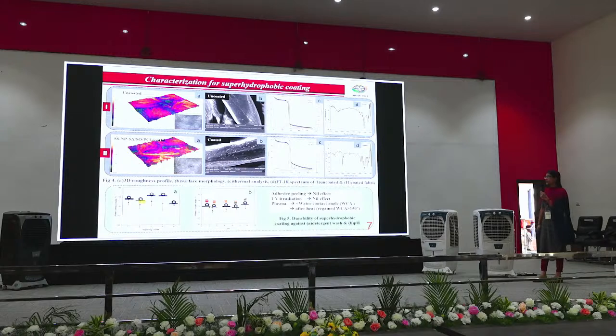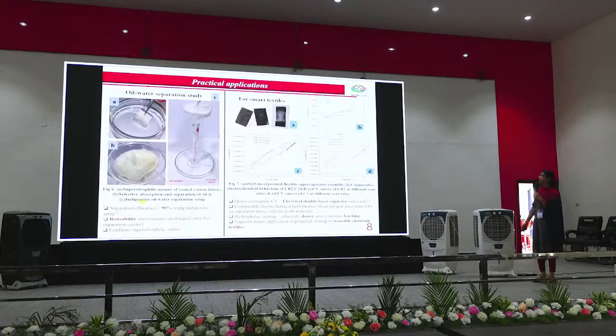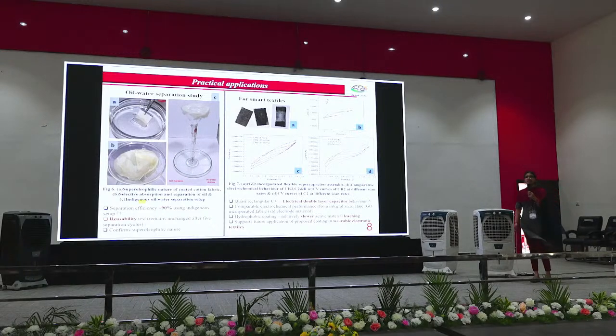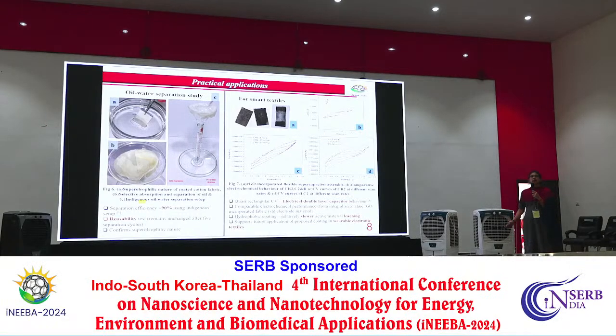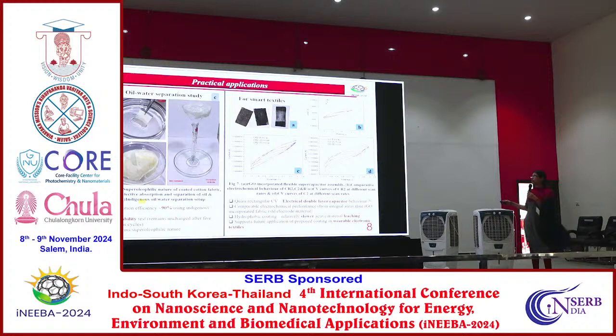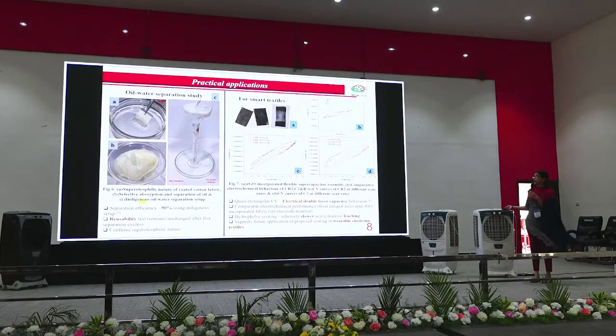And the coated surfaces were also tested for their durability. They can withstand more than 5 detergent washing cycles and acidic and alkaline pH. We also found the surfaces to be self-healable, that is, they regain their superhydrophobicity after heat treatment. To test it for practical applications, we proposed oil-water separation, and using an indigenous setup, we are able to achieve more than 90% separation efficiency, and this efficiency is reproducible after 5 separation cycles as well. Nowadays, smart e-garments are gaining more attention, and that's why we have proposed these textiles as a wearable conductive coating so that it can find future application in e-garments.